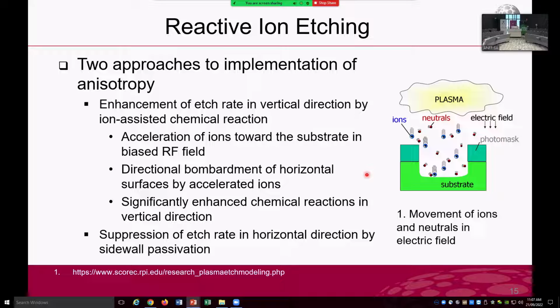In reactive ion etching, there are two approaches to enhance etch rate in the vertical direction. The first approach is the use of ion-assisted chemical reaction. After generating ions in your plasma, we direct them toward your target surface, and these ions will collide with the target surface in the vertical direction. The sidewalls are not going to be bombarded with this ion irradiation. Only the horizontal plane will be irradiated with these vertically directed ions.